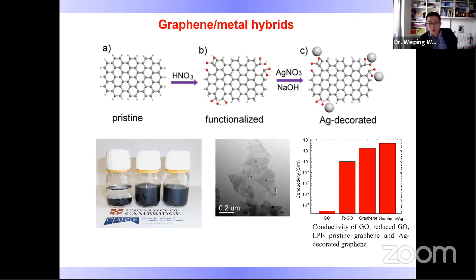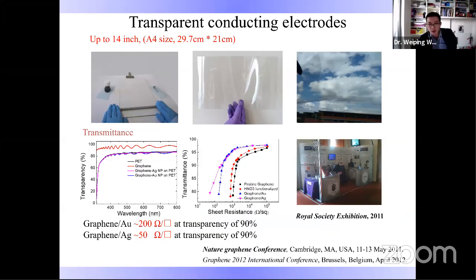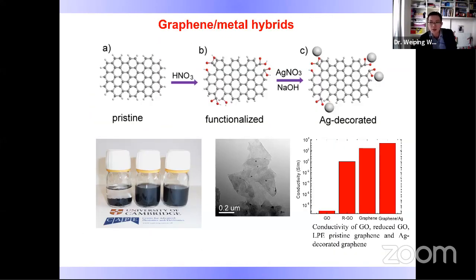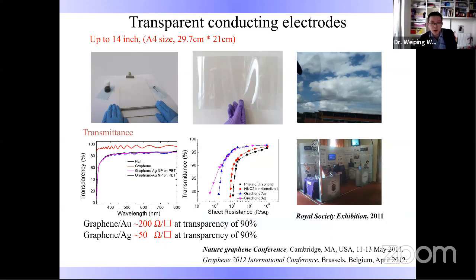So at Cambridge, I proposed a new method of attaching metallic nanoparticles to graphene that is exfoliated not from GO but from graphite, aiming to enhance graphene's conductivity for applications like transparent conductors and RF devices. This method tends to be very effective. By roll coating, this graphene transparent conductor shows a very low sheet resistance of around 50 ohm per square at a transparency of 90%.